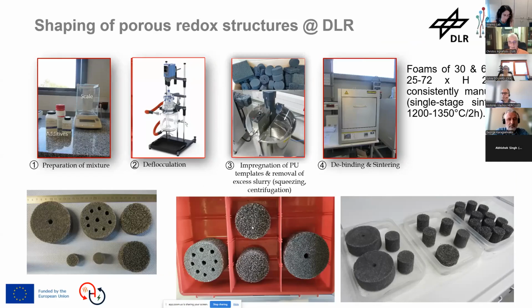They are not one-dimensional channels like the honeycombs, and these structures in theory enhance radial mixing and radial heat transfer. Okay, and you can see here the variety of the shapes that we can make with holes here and there to fine-tune the porosity along the periphery or to be fitted to different reactors with thermocouples and so on.